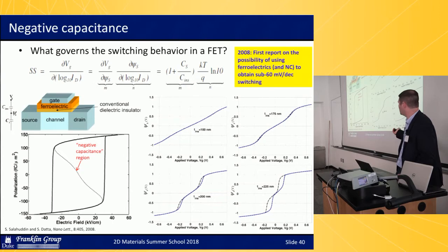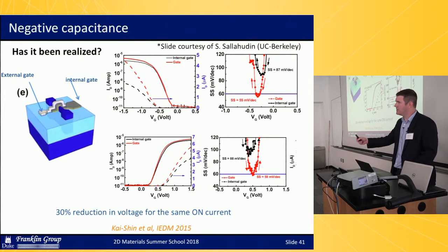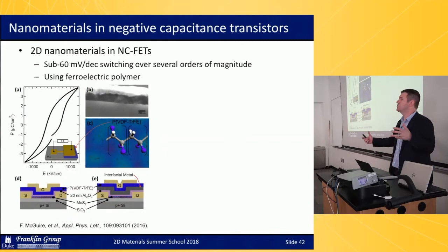Well, this is one of many of these papers that have been published that can show you using silicon FinFETs, so even down to some groups showing 22 nanometer technology, where all they did to change the silicon FinFET was add in a thin hafnium oxide doped material that's ferroelectric into the gate stack, and observed an improvement in the overall subthreshold swing, including some observation of switching below the thermal limit of 60 millivolts per decade.